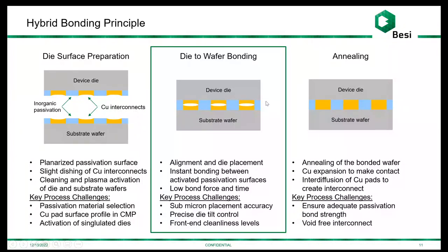And in die to wafer bonding, we first precisely align the device die to the substrate wafer. And we bring the die in contact to the substrate wafer. And when we do that, there's an instant bonding between these oxide activated surfaces. We can achieve that with very low force, typically in the range of maybe 10 to 15 newtons, and a very fast time. And we do this at room temperature. It's not a process that requires any heat. So it's really relying on the activation of the surfaces, the flatness of the surfaces, and the geometry.